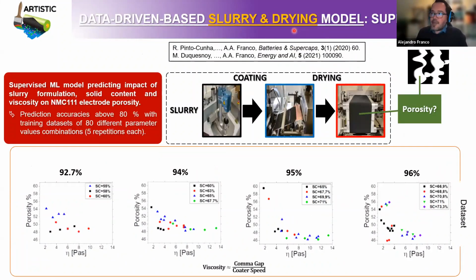So you can also address the problem of the slurry drying by using machine learning, and in particular supervised machine learning. And here I'm bringing to you a paper that we published initially in 2019, and the definitive year of publication was in 2020, because in 2019 the accepted version of the article was published. Here, what we want to do is to apply machine learning in order to predict the influence of slurry formulation, solid content, and viscosity on the electrode porosity. We also explore the impact on electrode loading. That's something that I'm not describing here in this slide.